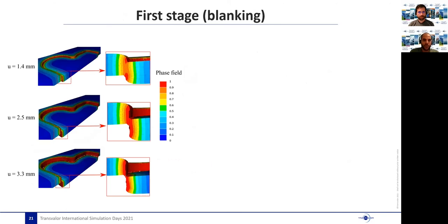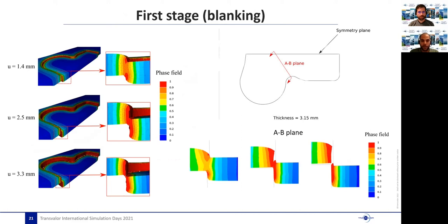We start with the first blanking stage. As you can see at the left, the initiation and propagation of crack surfaces can be accurately captured with our model where a perfect contact between the workpiece and the tooling can be expected at the shear surfaces. And here at the right, we can see the crack initiation and propagation through a cross section and at the interior of the material, but also we can see that the model is able to perfectly predict the crack propagation process. We can see that the surface with all the characteristic features, such as the formation of burrs, can be accurately captured.